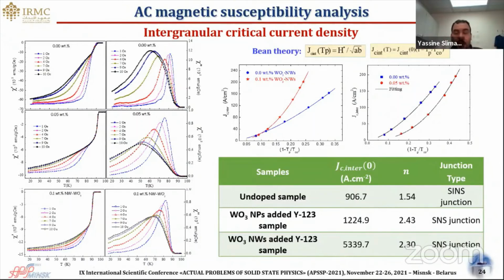With the help of SEM and TEM observation, as presented in previous slides, and also several other analyses, we established that the improvement in the values of intergranular critical current density, intragranular critical current density, and pinning force are mainly attributed to the variations in the composition of the grain boundaries due to the nanoparticles that reside among the grains, to the nanophases implanted in the YBCO matrix, attributed also to the intensification of the interfaces between the superconducting matrix and the implanted nanophases, as well as to the generated structural defects within the compound.